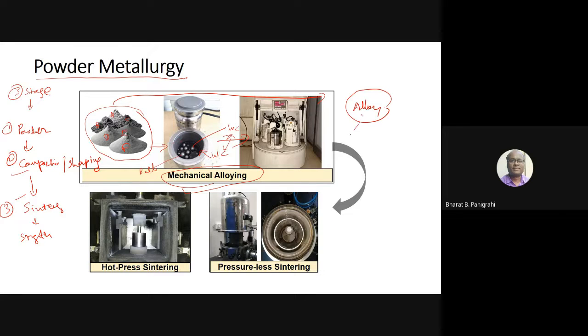Sintering can be done by something called pressureless sintering. You make a compact and sinter in a vacuum or inert gas. You can also use sintering through the hot press technique. So we employ both techniques. In hot press, powder is sintered while applying pressure at high temperature, whereas in pressureless sintering we do not apply pressure during heating. So there are two different sintering routes, called hot press sintering and pressureless sintering. We involve both kinds of process here. Both have their own advantages and disadvantages depending on what kind of component you are producing.